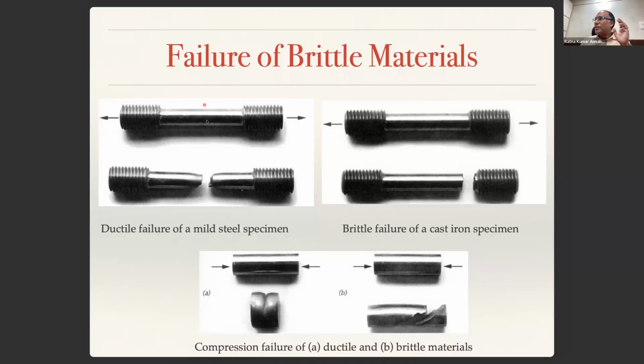Now, if you look at these two images, on the left hand side is a ductile material, a mild steel specimen, and on the right hand side is a brittle material, a cast iron specimen. If you apply uniaxial tension on both of them, you can see the ductile material breaks in a cup and cone at an angle of 45 degrees. That is because the plastic deformation happens first along a 45 degree angle.